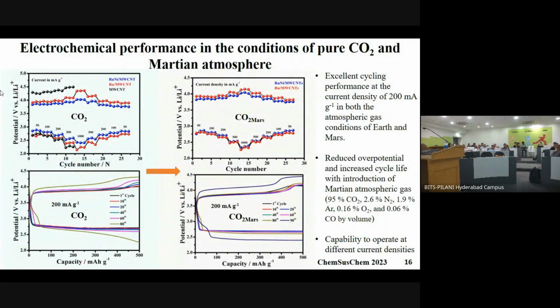And this is the performance of this ruthenium nickel multi-wall CNT catalyst-supported metal CO2 battery system. On this side we have tested the battery in a pure CO2 atmosphere, while on this side we have tested the battery in the Martian atmosphere. We have used a simulated Martian atmosphere with exactly the same gas composition, like 95.2% CO2 plus some 2% CO and some other gases.